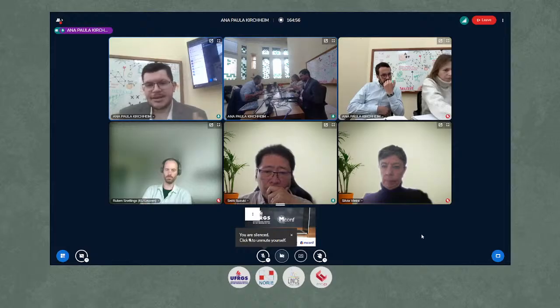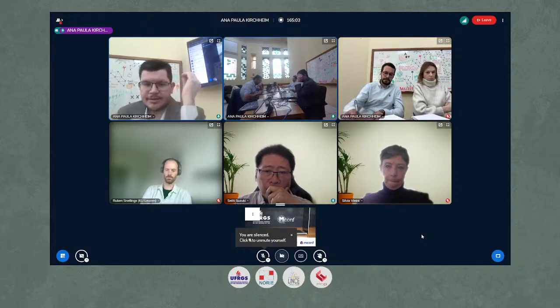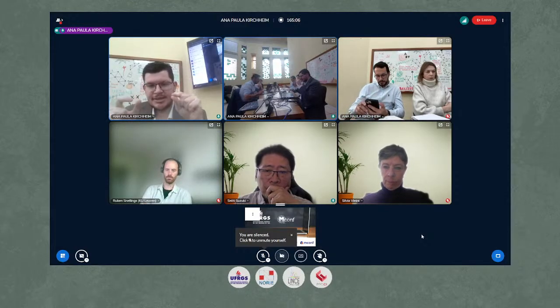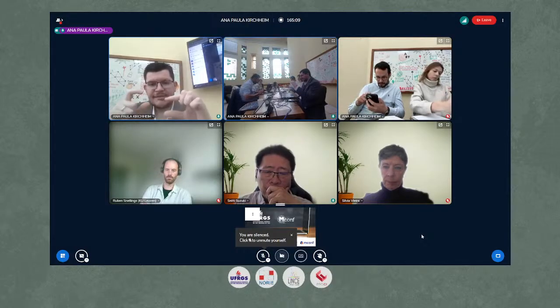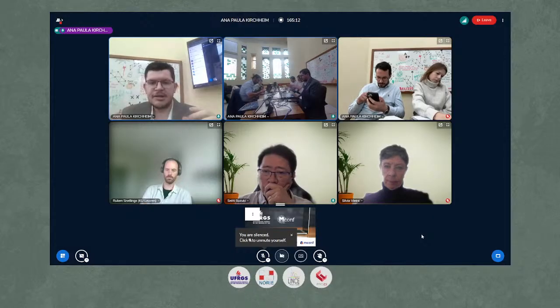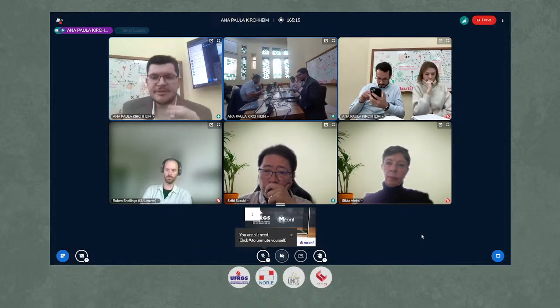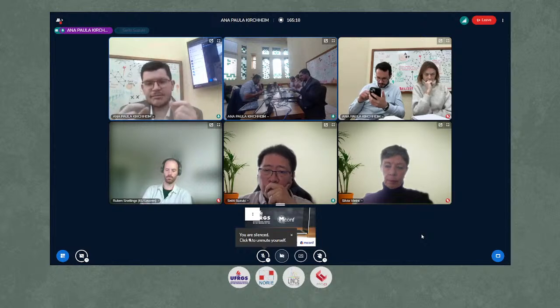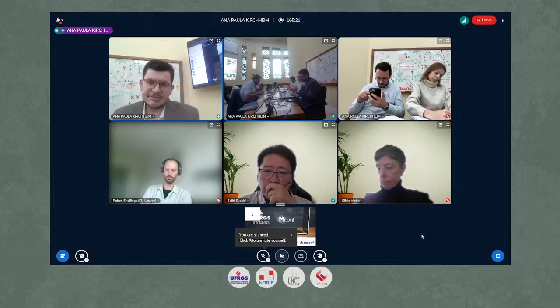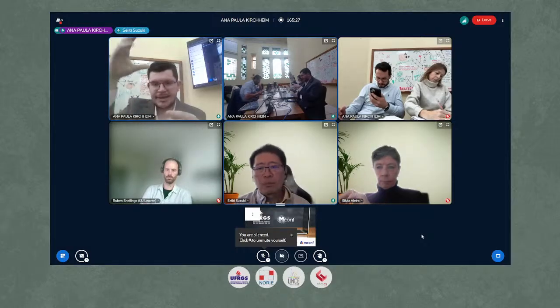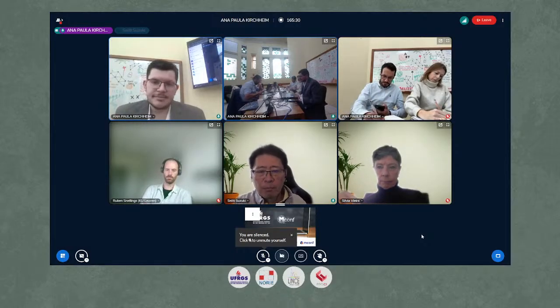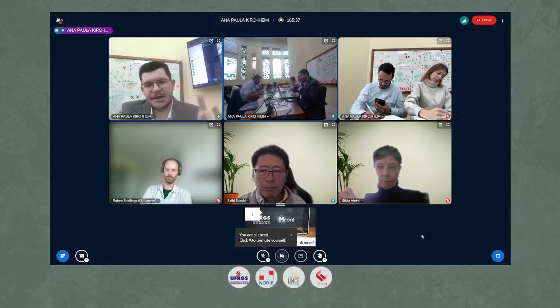And so I believe it has these limitations. I don't see it as "this doesn't have correlation," meaning that if I have a cement and I increase this parameter, it won't affect it. It's just that in this data, I believe I should make this clear, this wasn't more important than the other parameters. But obviously, if you have a clinker and you have more belite, if you increase belite and decrease alite, it will be harder to grind. The same for the sulfate: if you have a clinker and increase C3A, you probably will need more sulfate to be optimized.